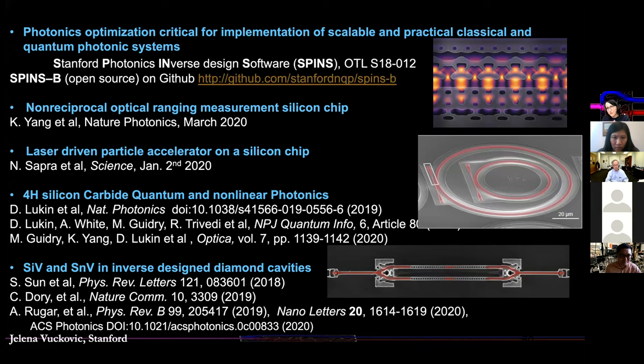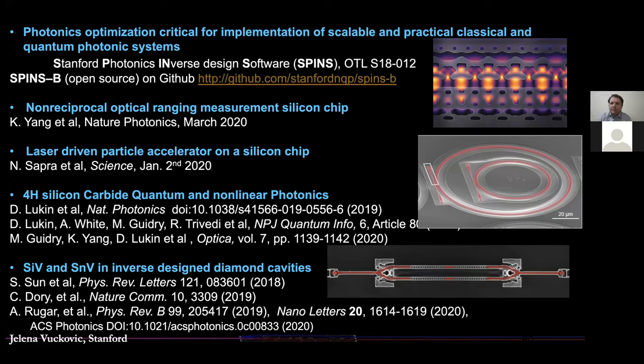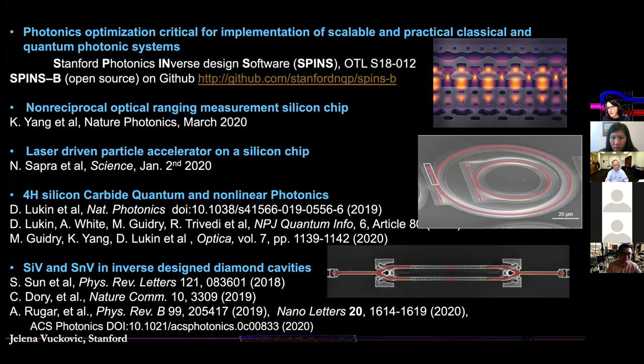But then there are issues with non-radiative decay and internal efficiencies, and some of the line widths of the color centers are not as narrow as they are for quantum dots. So we do think that we can actually reach the strong coupling regime. We're not there yet and nobody has demonstrated it yet.